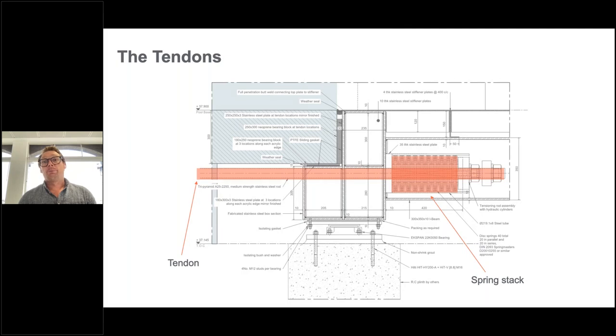And this is a section through the pool and through the steel tub. And as I mentioned, the acrylic can expand by 65 millimeters. So how do we create a unified structure out of these individual components? Rather than bolting the steel to the concrete, which the acrylic wouldn't have dealt with too well because of the localized stress, we decided to put tendons in. So we're essentially pulling the tubs onto the acrylic. And so if the acrylic extends, we can control the amount of additional load that goes into the tendon. Obviously, if the swing pool shrinks, we can also control the loss of tension in the tendon, so there's always compression in the overall structure.